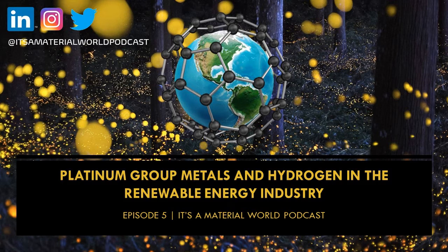And that means that these catalytic converters are basically a ceramic block on which you have some noble metals, platinum, palladium, rhodium, deposited as a catalyst. And these metals, with the right electronics and what have you, convert these materials, the hydrocarbons, the CO, the NOx, into nitrogen, CO2, and water. And in the latest models, there is also quite a lot of attention for the emission of soot particles from diesel engines, but gasoline engines also make some of these microparticles. There are specific active filters that convert those particles into CO2 and water as well.